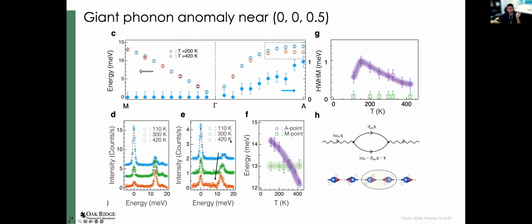But if you look more carefully, you find that near the half-L peak, you do have quite a large phonon anomaly. Whereas if you go to the endpoint corresponding to the 2x2x2 CDW, or the connecting nesting wave vector, there is really no phonon anomaly associated with that. Here we show a couple of experimental raw data, and you already observe that the phonon goes softening as you go to higher temperature.